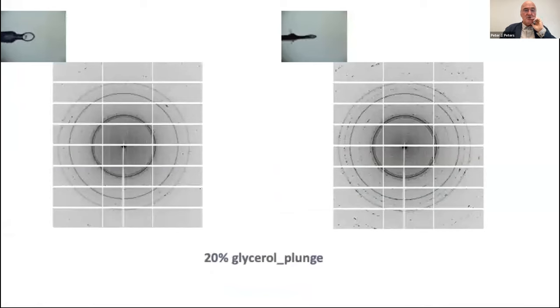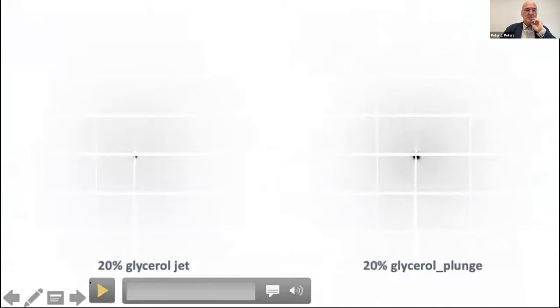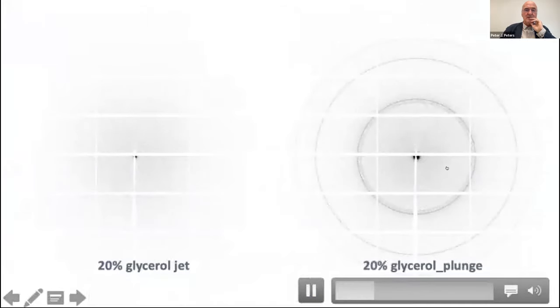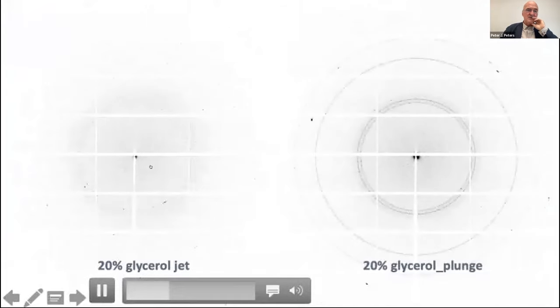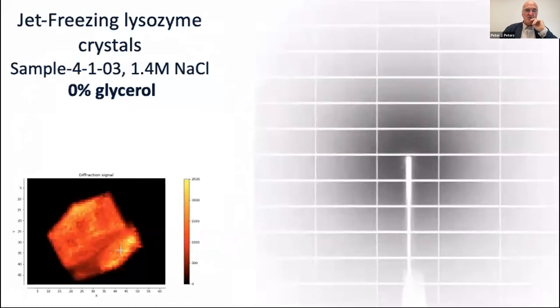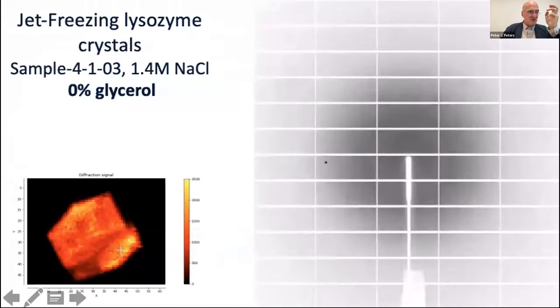When you plunge 20% glycerol, you can see the water ice crystals in these two cases. Also, if you look at movies, you can see the rings typical for crystalline ice. And here, when you jet freeze, you can see the pattern that is precisely what you expect from amorphous ice. So we also tried this for a purified, crystallized protein, and the crystal is seen here.